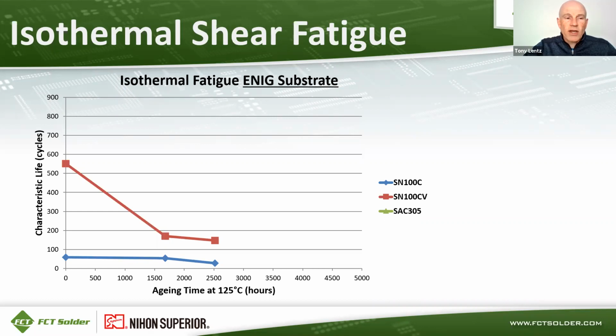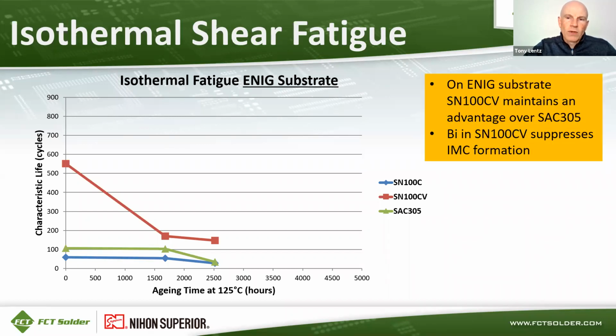SN100CV on an ENIG substrate drops off and then stabilizes above the SN100C life. And then Sac-305 is pretty similar to the SN100C. It's a little higher initially, but then it drops off to match the characteristic life of the SN100C. So on an ENIG substrate, SN100CV still maintains an advantage over Sac-305. It's the bismuth in SN100CV that actually suppresses the IMC formation and helps to lengthen that life or make it a little more stable.